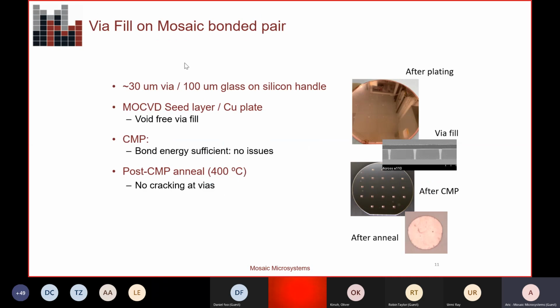Here are some examples of us doing what I just described. The top picture shows a 100 micron thick glass wafer on a silicon handle after PVD seed and bottom-up plating. This is a 30 micron via in 100 micron thick glass. I think this was a 6-inch wafer. The second picture shows a cross-section of those vias, and you can see an important aspect here is that these are fully filled vias.